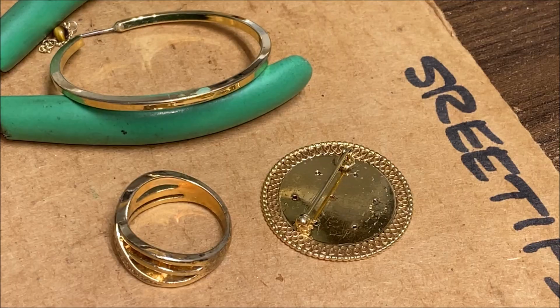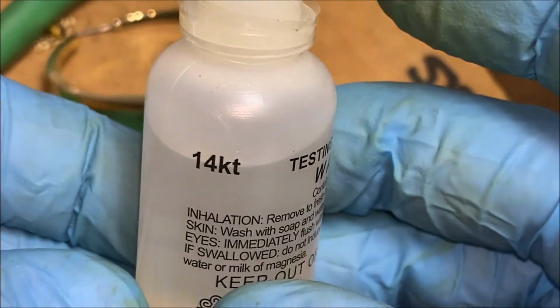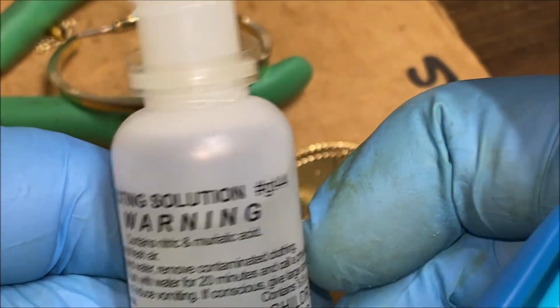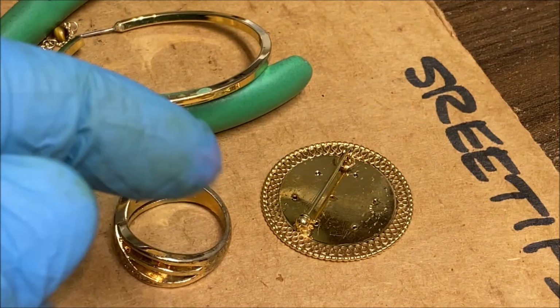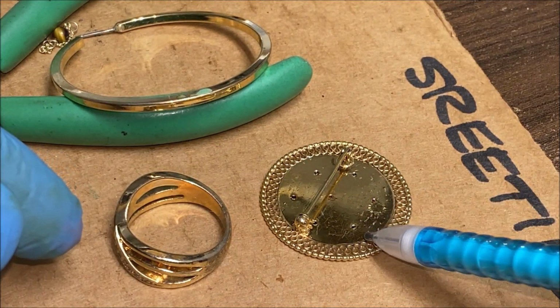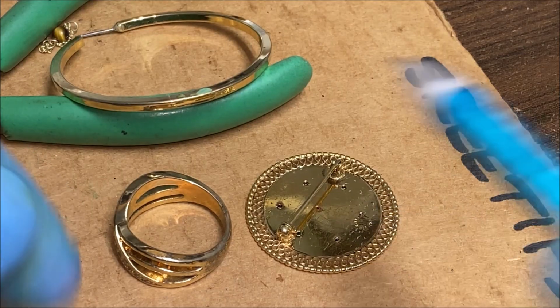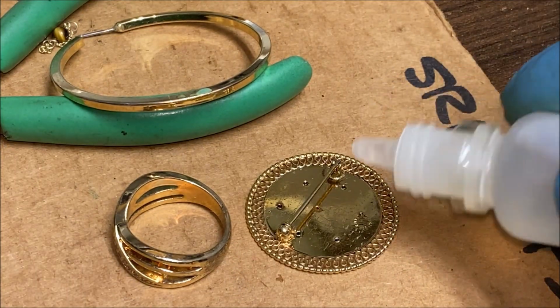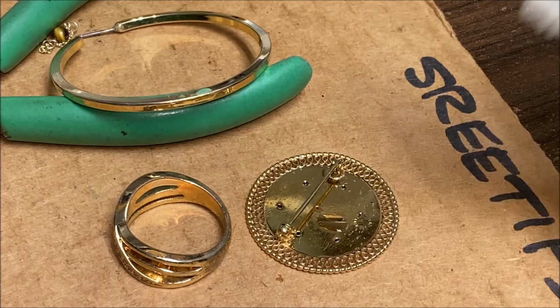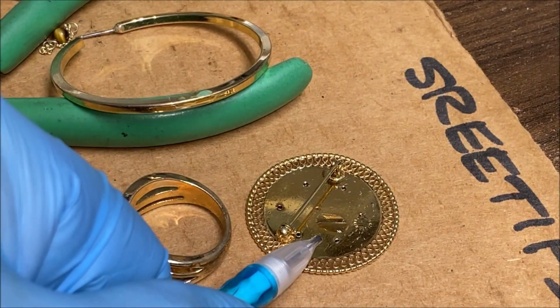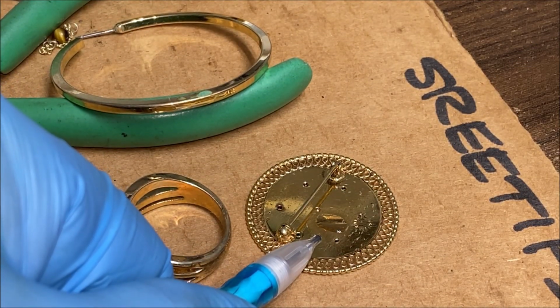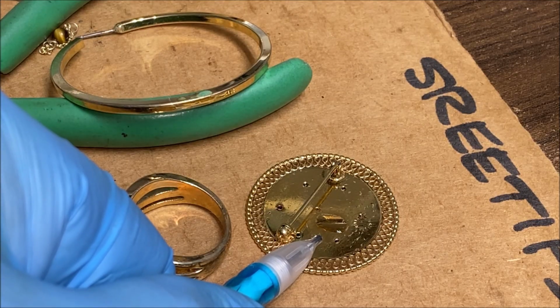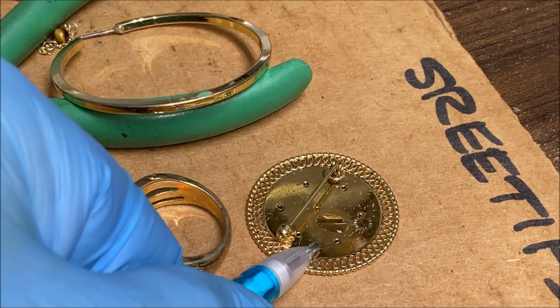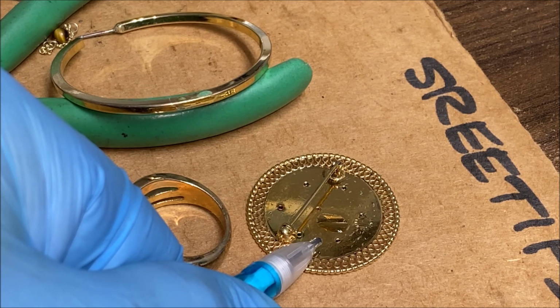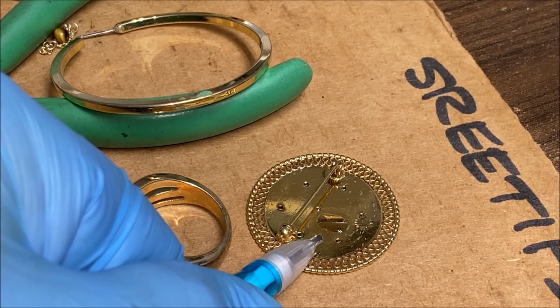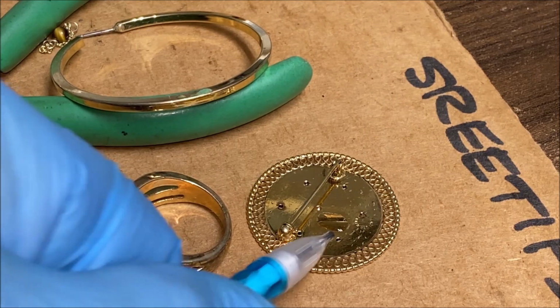Another simple test we can do is use some 14K gold testing acid here. And I've got a piece of known gold filled material clearly marked right here. If we put a drop of the acid right directly on the piece, you'll notice it will just sit there and not react. That's because this is karat gold over brass, and the karat gold will protect the brass underneath.